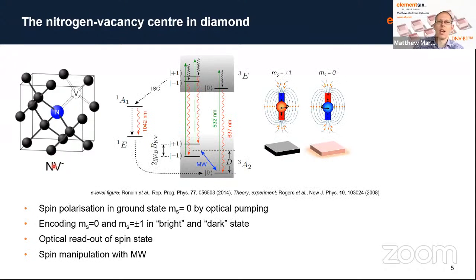It has a very interesting energy level structure, such that when you illuminate the NV defect with green light, which can be laser light or a green LED, if it's in this ground state, you get excitation to the excited state, and then it drops back into the ground state, emitting a red photon. However, if it's in these particular states here, then you go via this intersystem crossing state down here, back into this ground state. So you've got a very simple energy level structure, such that just by pumping it with green light, you can put it all into one single spin state.